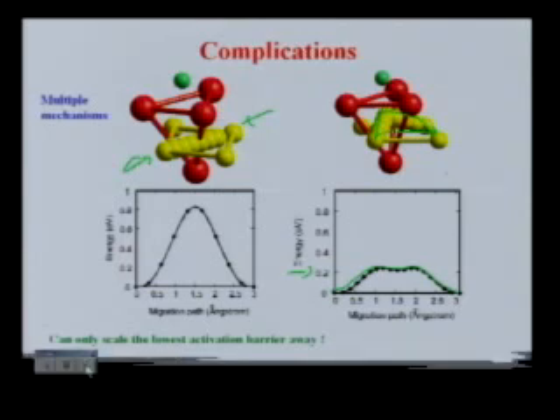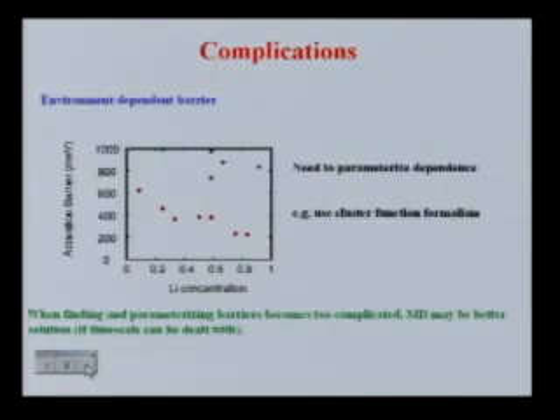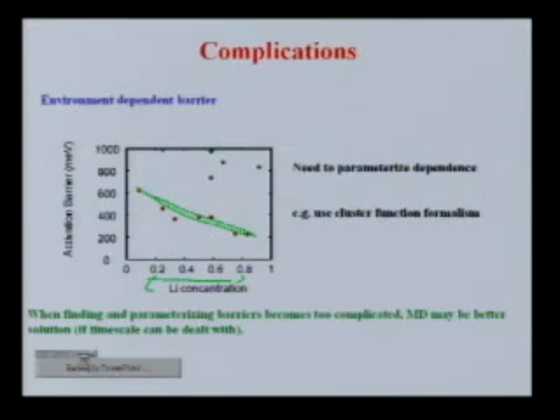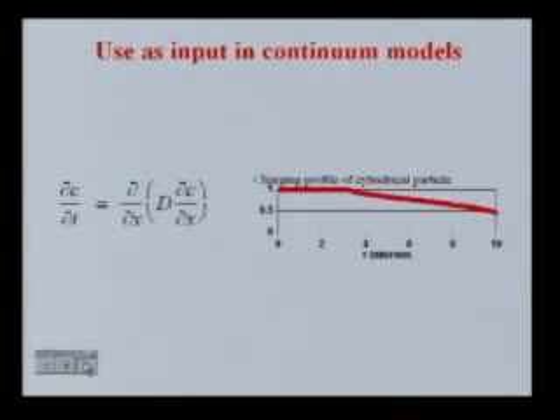But this works—you can get diffusion constants, this is with the elastic band method. This is the activation barrier for that low energy mechanism as a function of lithium concentration, so it's very dependent on concentration. So you can do your kinetic Monte Carlo, and then you can go all the way to macroscopic simulation. You can solve Fick's equation and look at diffusion on the scale of microns. So it's a fairly simplistic way of coarse graining.